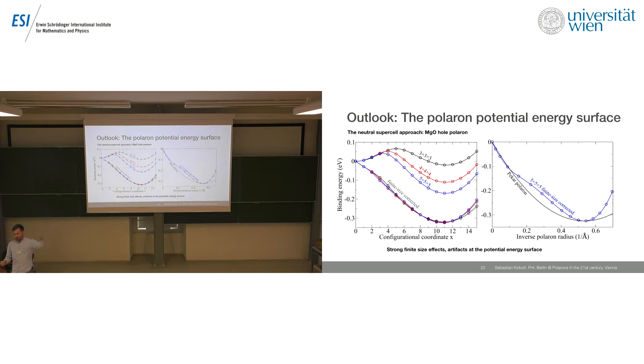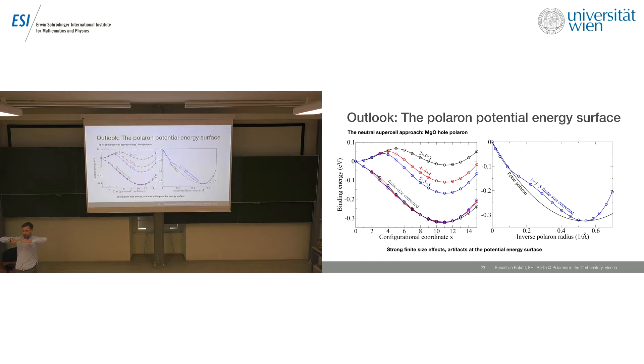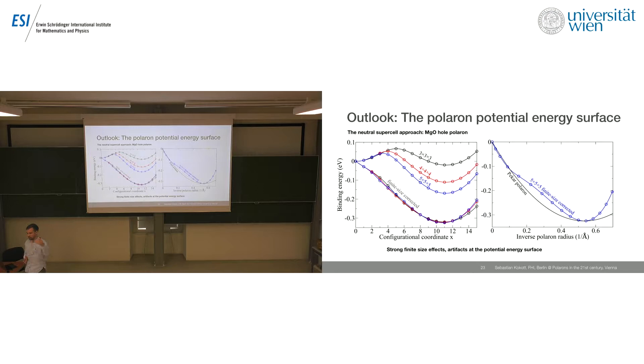Christoph Freysoldt showed also in his paper that you can use basically this correction scheme also for the delocalized case. And why this is the same here is - if you watch the movie you get this kind of envelope, and it starts to form continuously, as you would expect in the adiabatic potential energy surface. And if it is really delocalized, you can apply the same correction, giving you basically no substantial difference. So there is no limitation in this Freysoldt correction scheme for more delocalized states. All these correction schemes are benchmarked by comparing with increasing cell size - still there is this point that increasing the cell size shows no difference, and then the dilute limit point is much lower. So basically you have a model charge distribution from which you can calculate the lattice sum - the spurious interaction of all the images. This you remove and add the isolated one.